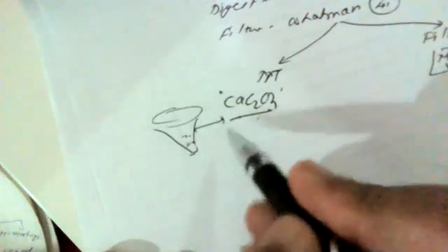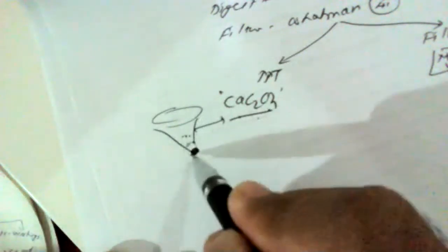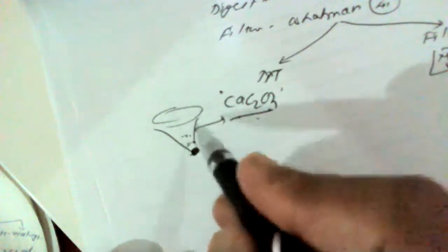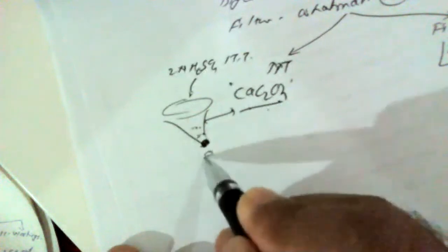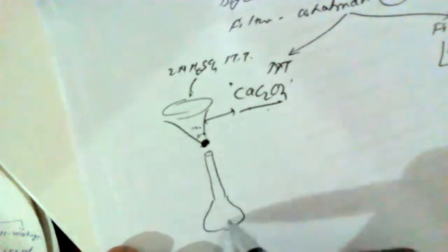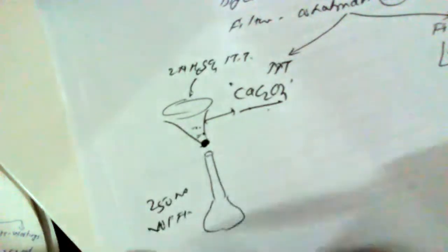Now we have to treat this calcium precipitate. So the calcium oxalate precipitate, say for example, this is our filter paper. Here the calcium oxalate precipitate is there. Again we have to pierce this filter paper, that means we have to turn this filter paper, and to this precipitate we have to add 2 normal sulfuric acid, around 1 test tube, because 1 test tube of sulfuric acid is sufficient to dissolve this calcium oxalate, and this is to be collected. All this content is to be collected in a 250 ml volumetric flask, and these contents are to be diluted with water to 250 ml.